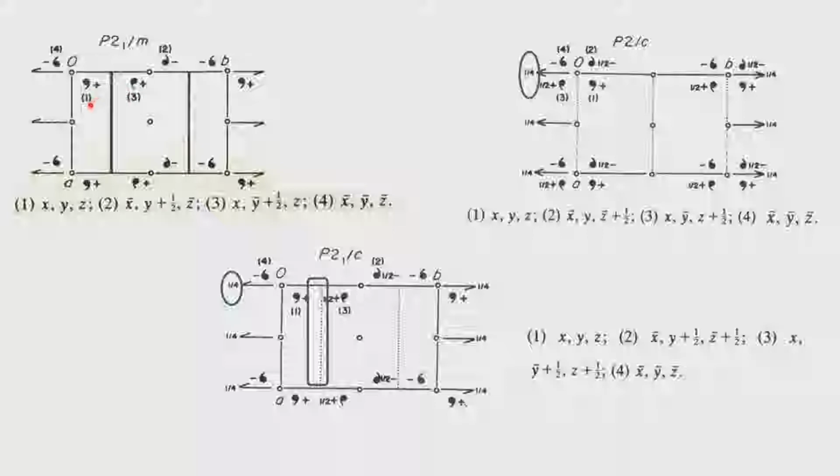Therefore, the symmetry operations now become slightly different. So, if you take the point number 1, operate now the presence of the 2-1 screw axis. The 2-1 screw axis will take this, rotate by 180 degrees, translated by this unit. The rotation of 180 degrees is as usual x bar and z bar, and the addition of half unit is y plus half. So, you get to this point number 2. 1 unit translation of the point 2 will bring it inside the unit cell. So, we have generated 1 and 2 inside the unit cell.